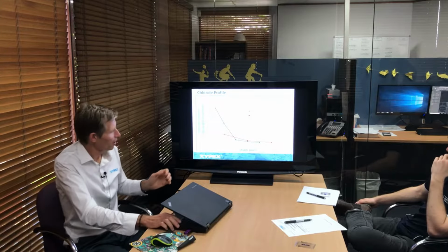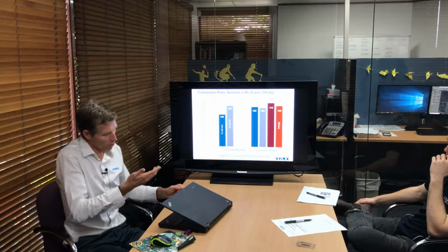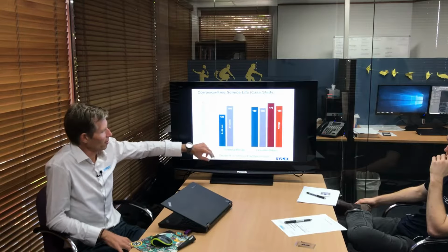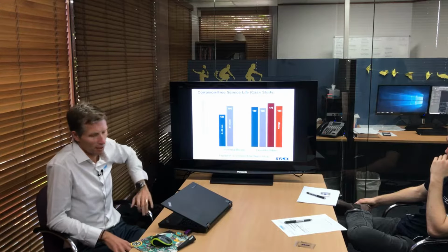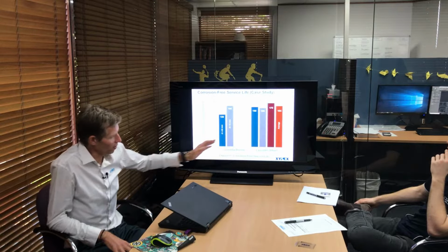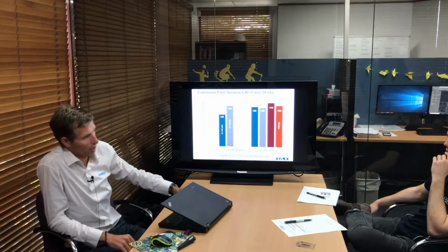Now really after 20 years, that's probably not so bad, but it's good looking at these things in the chart, looks fine, but what does it actually mean to the client? So as I mentioned, when they do the calculation and take these results, we'll put all in there. At Cronulla Marina, after 19 years and 40 mm cover, the corrosion-free service life forecasted is 129 years. At the other structure, using the nature of the structure and the testing that was done, they took a wider range of samples, and that averaged out at 164. And I must stress, that's after 19 years.